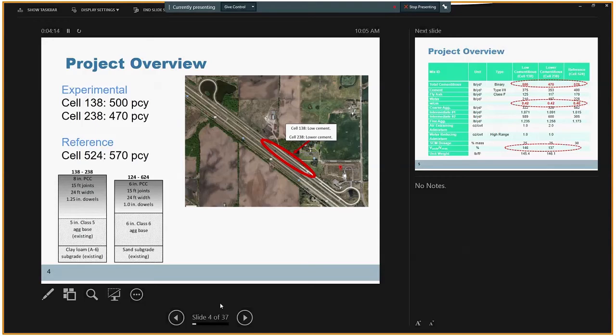The two experimental sections, cells 138 and 238, had an 8-inch thick concrete pavement, and we had 1 1/4 inch dowel bars in joints. The joint spacing was 15 feet, and the width of the lanes was 12 foot. For the reference concrete, the joint spacing and the dimension of the panels were the same. The dowel bars were 1-inch dowel bars, and the thickness of the pavement was slightly less, 6 inches. Experimental cells were cast over a 5-inch thick class 5 aggregate, but the reference cell was cast over a 6-inch class 6 aggregate base.